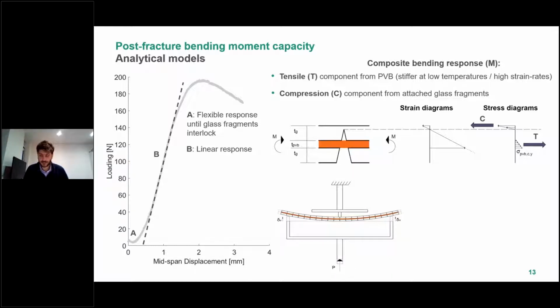The bending moment capacity was derived for this stage under the assumptions of plane sections remaining plane and by applying the transformed section approach commonly used in analysis of reinforced concrete. The compression component in the bending moment is provided by the glass fragments that come into contact as the panel deforms, and the tension component is provided by the interlayer. A nonlinear response is observed in the next stage due to the change in slope in the PVB material model. Although this transition point is often referred to as yield stress, it only refers to the stress at which a significant change in modulus is observed rather than the onset of true plasticity.